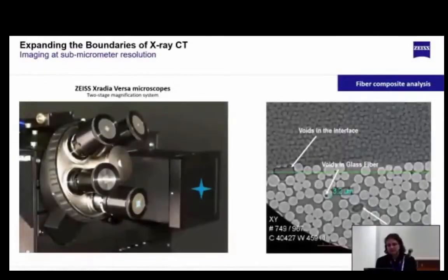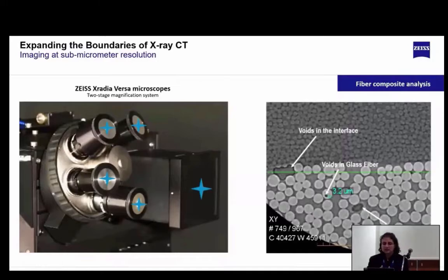The scintillators for each objective in the X-ray microscope have been optimized to provide the best contrast. So by adjusting the lens to detect the appropriate X-ray energies at that level of resolution, we enable high contrast data as well. So this permits getting higher quality than you could achieve with traditional flat panel detectors.